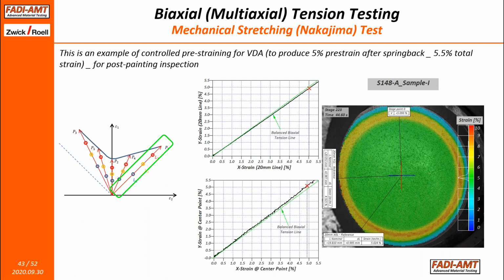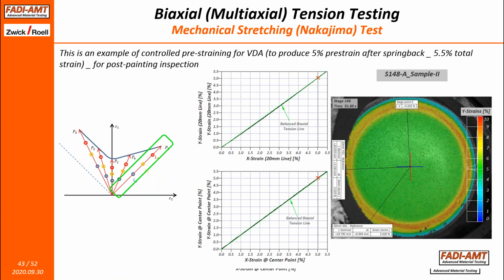And this is another case without a video, just images, showing how you can achieve a pre-strain level. Sometimes there are tests that require you to pre-strain the material to a known value. In this case, it was 5%. And we show here a couple of examples of how this was done, where the material followed a perfect biaxial profile.